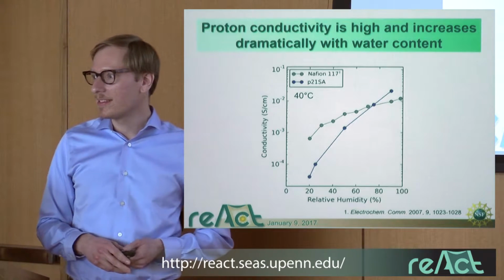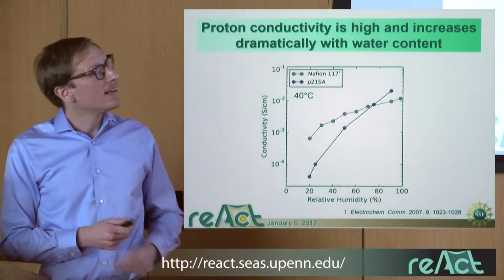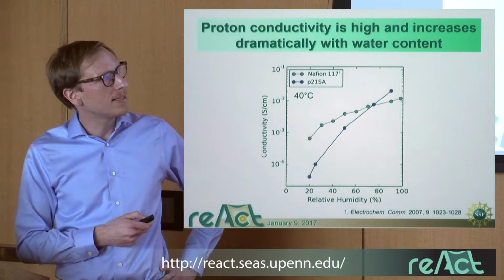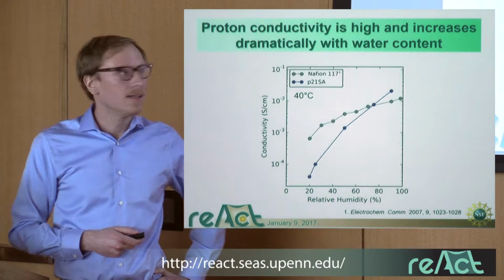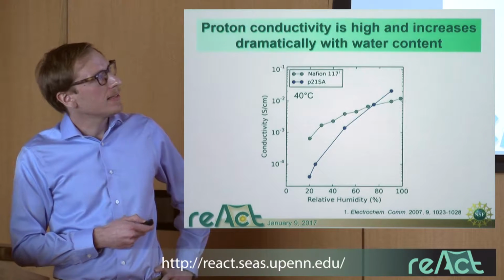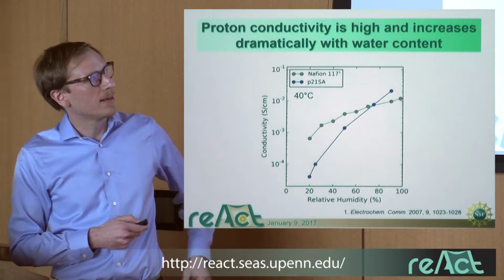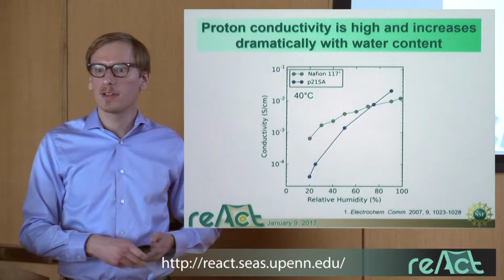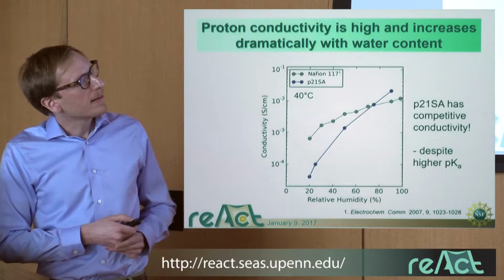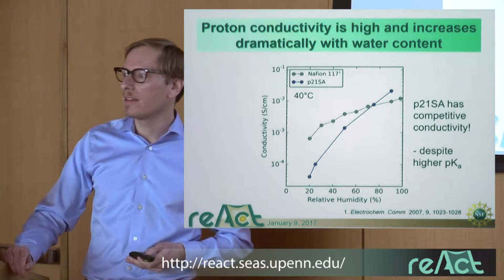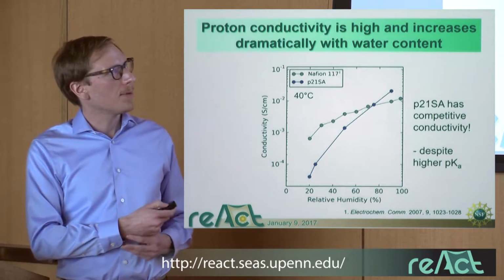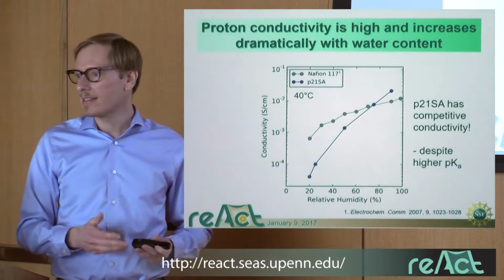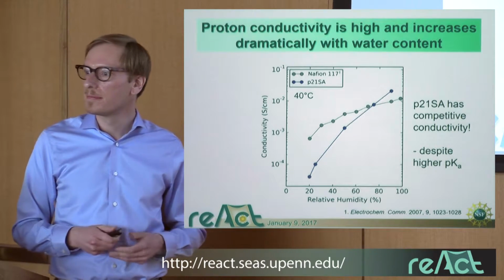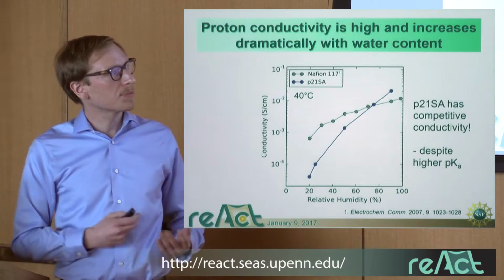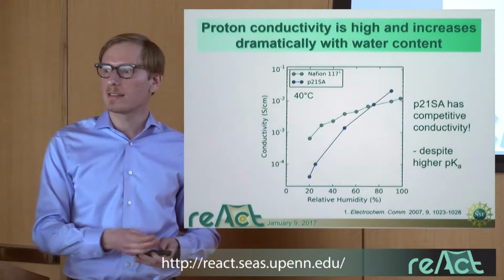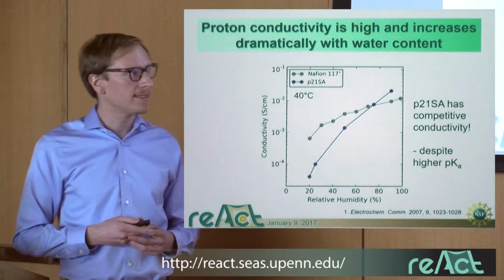And indeed, the conductivity is really very promising. At high humidities, we have conductivity exceeding that of Nafion. And we have a very steep dependence on the humidity, in other words, on the water content of the membrane. And this high conductivity is especially remarkable given that being a hydrocarbon, our polymer is a weaker acid than Nafion, which is a fluorocarbon. So this is promising. Let's look more closely into this layered structure and understand it in more detail.